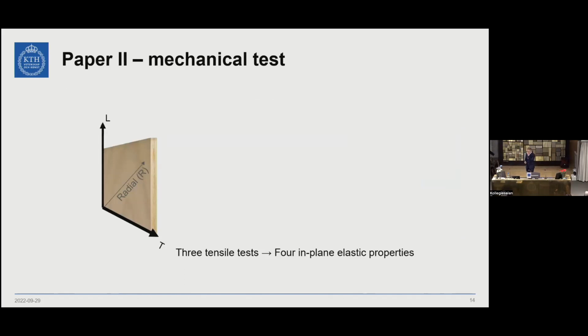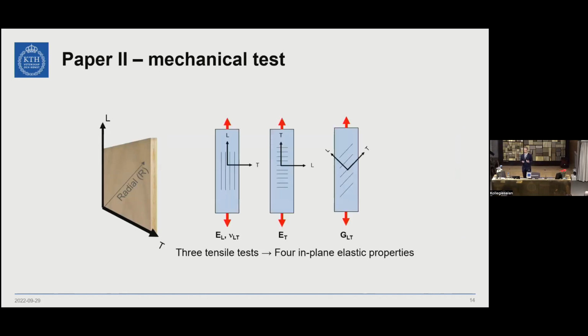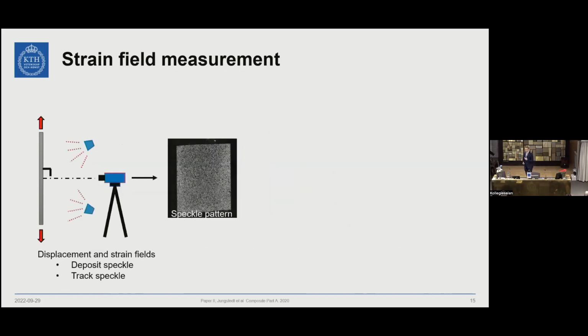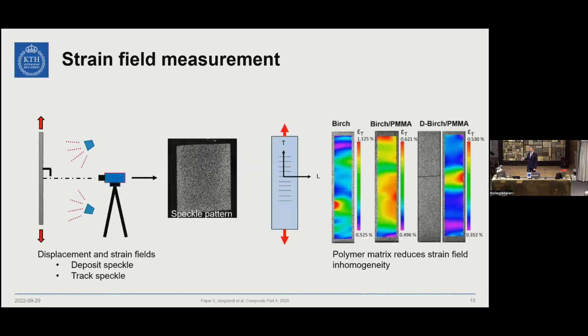Right. So we know that the material, the single ply, is orthotropic. So for us to investigate the elastic properties or the strength properties, we need to do 3 tests in order to get all of those properties needed to describe the material in plane. We also use strain measurements to see how it deforms. We deposit a speckle pattern on the surface of the specimen, and we then use algorithms to track those patterns.